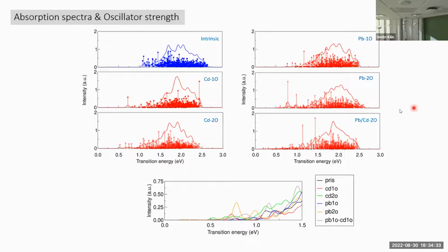In cadmium 2O and this interface, they don't come from the molecule, but in the other cases, they come from the molecule. If it is just a transition from a molecule, then it is very off in energy, because for this molecule, I think the transition should be in the visible range. 0.7 is definitely too much redshifted, so the functional definitely is not the right functional for this case. For the pristine quantum dot it's hard to say because of the confinement effect, and lead selenide is known for a small band gap. But for the molecule, for sure, it is a very unrealistic result.